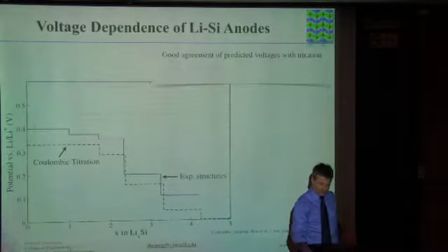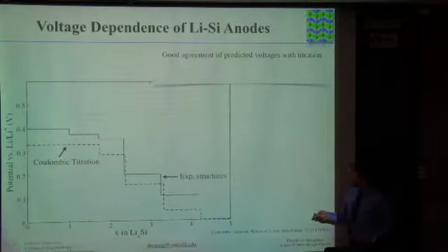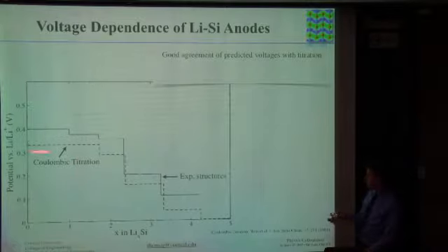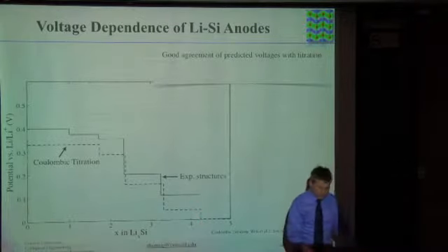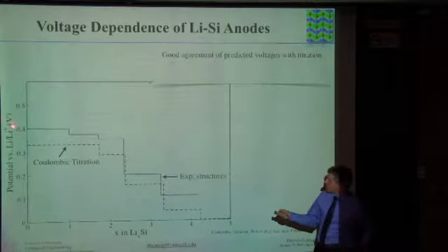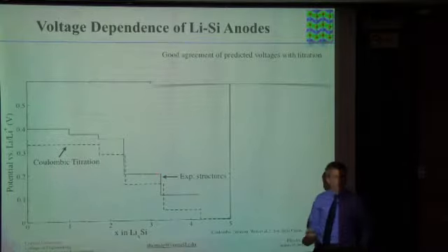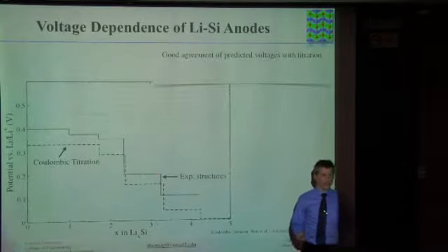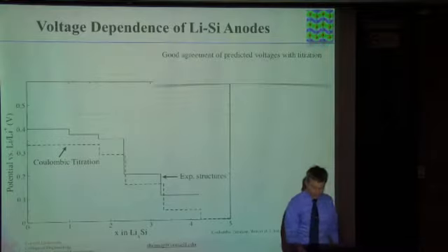So the next thing we're doing is looking at the voltages. And so I'm going to show you two curves here. One is Coulombic titration. It's high-temperature experiments, where the voltage drop in each of those steps corresponds to a phase transformation. If I use the experimental structures at 0 temperature, I get this curve. And you see, within about 50 milli-electron volts on average. And this is due to entropy, the deviation of about 50 milli-electron volts. So that's good enough for experimentalists.